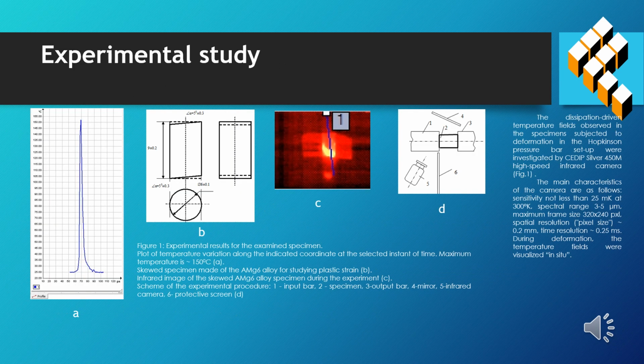The mechanisms of plastic strain localization in the material subjected to dynamic loading were studied in a split Hopkinson pressure bar using the specimens made of aluminum alloy AMg6, which exhibits the plastic flow instability. The skewed specimens were used to initiate the plastic strain localization at sufficiently high strain rate.